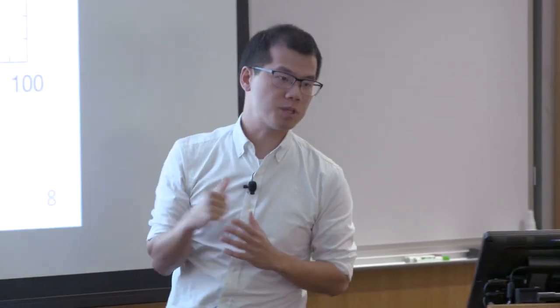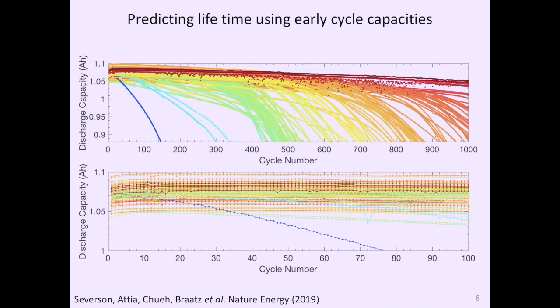Now, if I zoom in on just the first 100 cycles, okay, so that's just the first 10% of this plot, and say, ignore the rest, can I predict the behavior of the battery? On which one's going to last a long time, which one will last just briefly? The colors are coded in such a way that blue is short lifetime and red is long lifetime. And if you look at the first 100 cycles, so this is blown up 10x, you can see there's no order in the lines. The only thing I can predict is this one here, that this is really poor. But between red and green and blue on the top, I can't really tell. So simply by looking at how the capacity of the battery degrades, it's not sufficient.